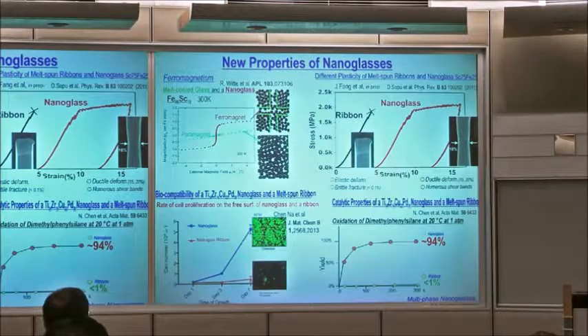No, you see, it's not toxic. The cells grow like mad. So why is this nanostructured glass better, even better than the ribbon? Is there any mechanism behind it? Right. Yeah, but that's not surprising. First of all, the fact is that cells prefer to grow on the nanostructure than on the non-nanostructure. And there are some studies in the literature by the group of Spatz. What he did, he took a crystal and he put small gold particles on it. And then he changed the spacing and the size of the gold particles, and then put a cell on it and asked which spacing and which size of gold particles does the cell prefer for the growth.